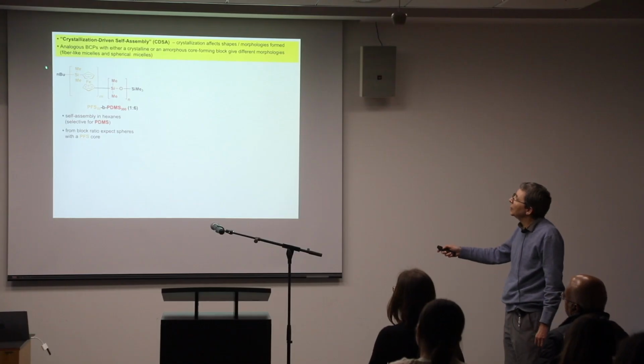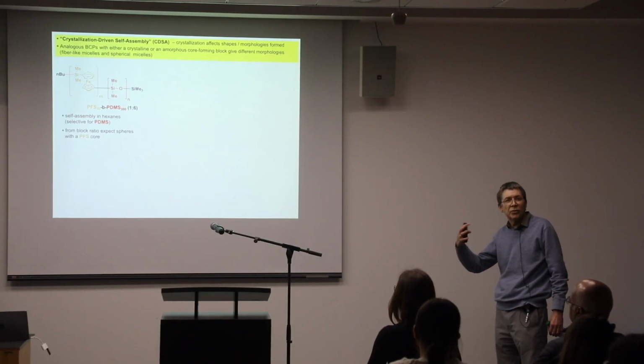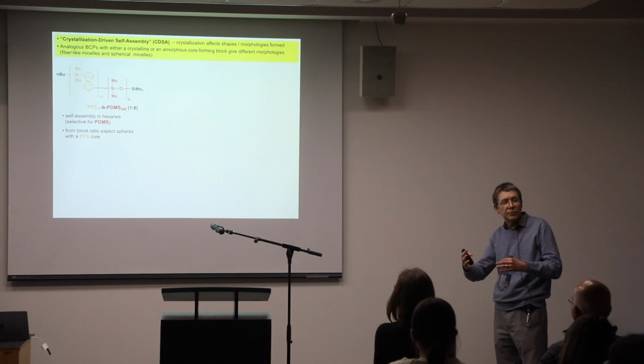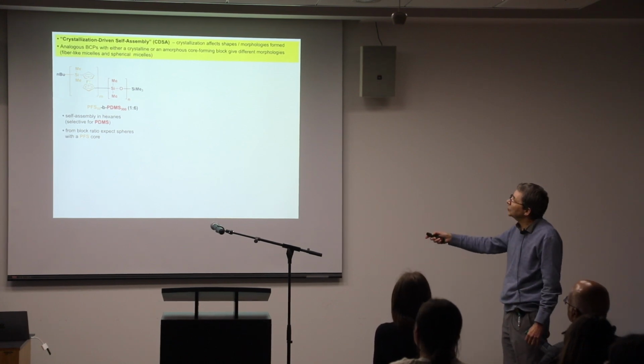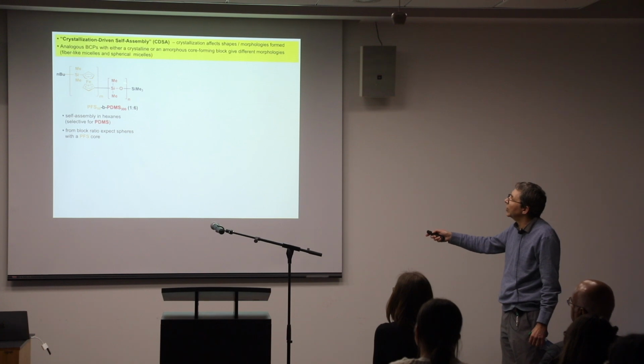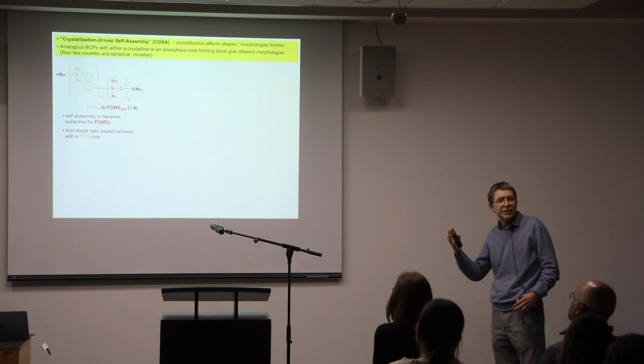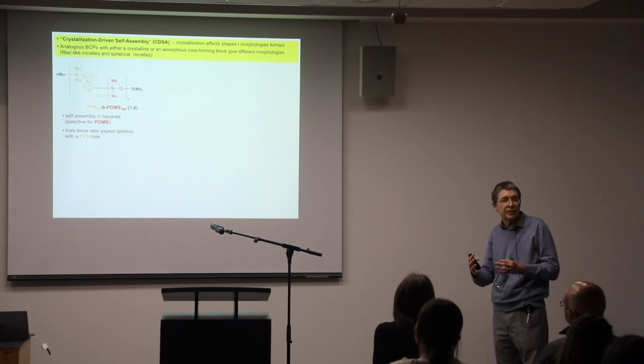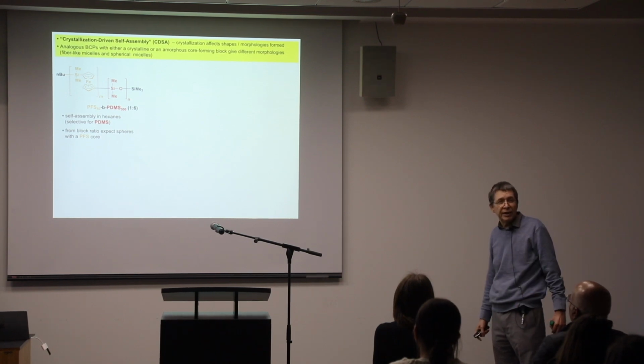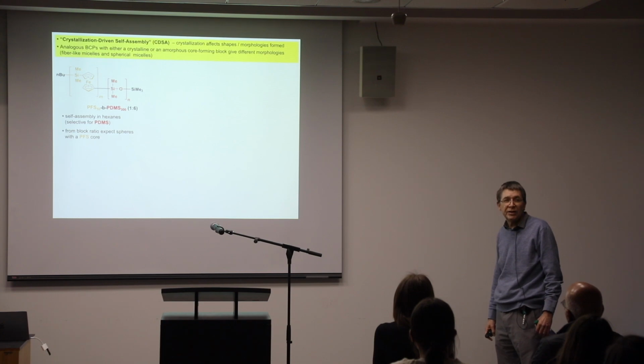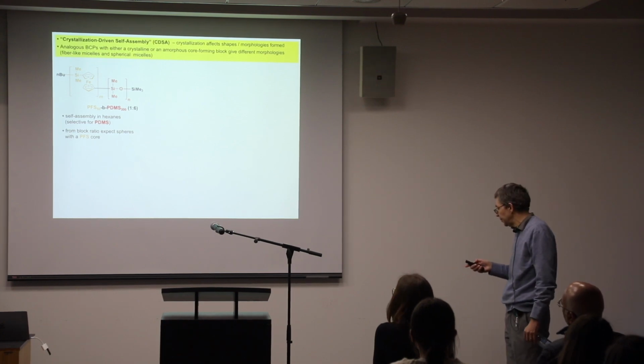So when you take this block copolymer and dissolve it in hexanes, you expect to form micelles where this forms the core and this forms the corona. And what we were expecting was to form spherical micelles. This is the most common morphology or shape you see for micelles when you self-assemble block copolymers.